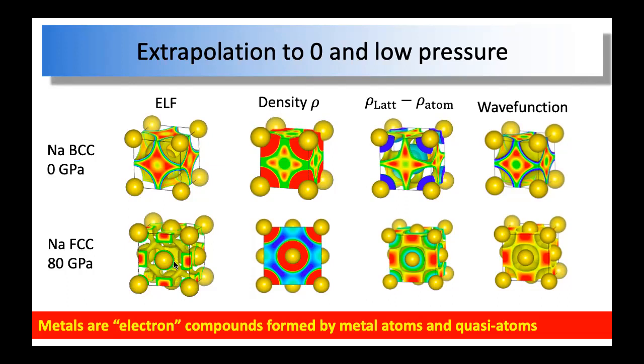And we will see that it's not true. It really depends on the metal you're talking about, and especially depends on the lattice parameter. So while you change the lattice parameter, you're going to change the electron localization at the different sites, and that really determines eventually the structure evolution. And again, if you carefully tune the density, you can see that the density shows a slight maximum here. It is a maximum, but the value difference is very small.